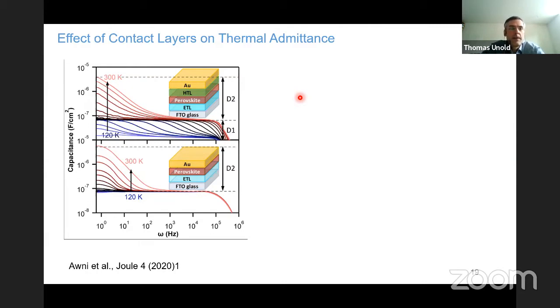And just one more thing about capacitance. You can also measure the frequency dependence or temperature dependence of capacitance. And the hope is that you get some energetic information about defects and doping levels in your device. So here is shown the capacitance versus frequency for a perovskite device. This is a recent publication, actually from last year in Joule. And then you get these steps, and they're usually interpreted as defects. So you can take a derivative and it will look like a density of states and so on. So here this is called the D1 and D2 step. And what they showed in this publication is that this step actually completely goes away if you leave off the hole transport layer, as shown here. And then in this publication they also show that this step here is really due to ionic motion and so on. And so that's another caution you really have to have about the frequency dependence of capacitance.